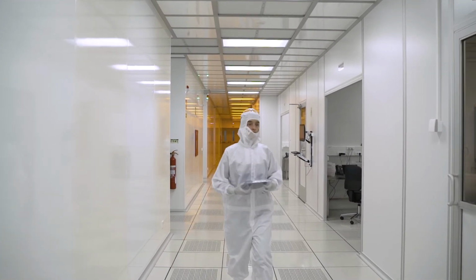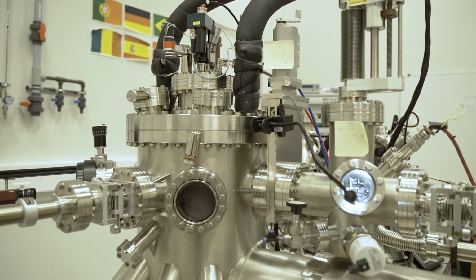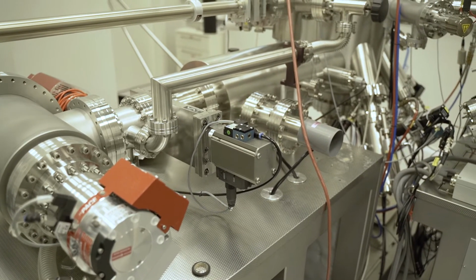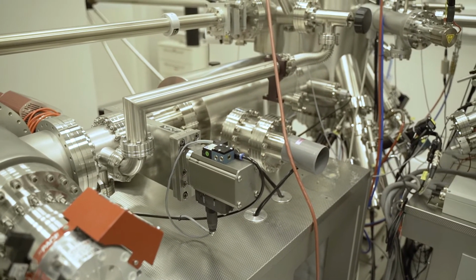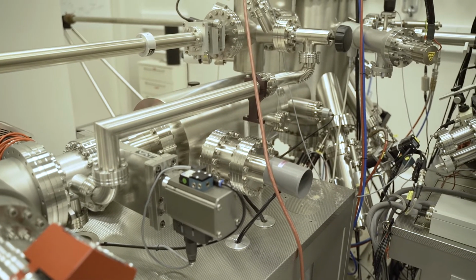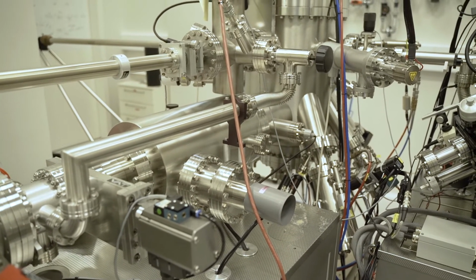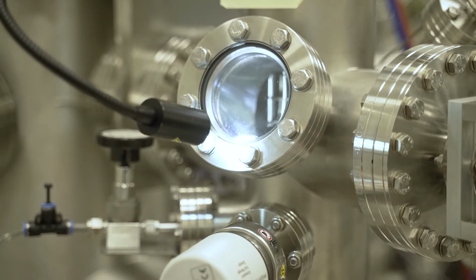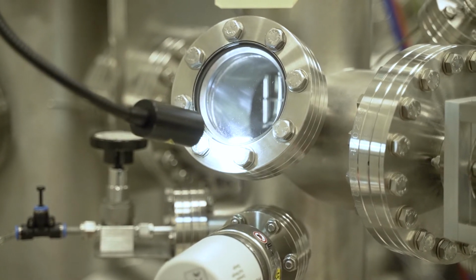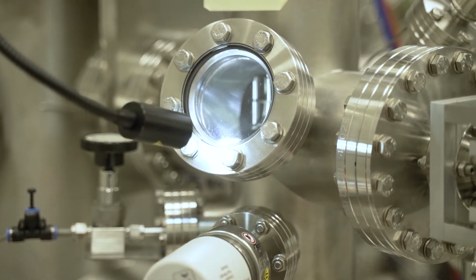So here I do 2D films. We usually do indium selenide or gallium selenide. And this is a machine that's called molecular beam epitaxy. The principle is that we throw beams of elements on the surface of a substrate, and these elements organize into the 2D materials that we want.